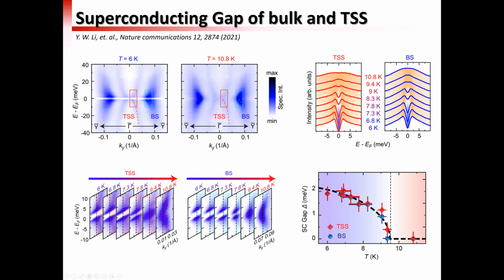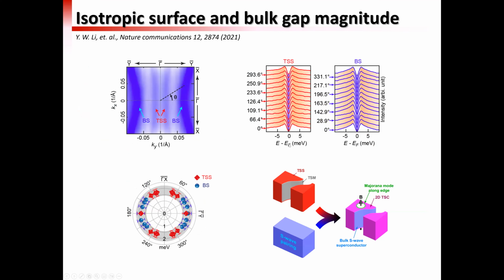And then if we just extract the data from this measurement and plot them together, you can see that starting from around 8.8 or 9 Kelvin, the gap starts opening. Interestingly, the gap magnitude of the topological surface state and the bulk state are very similar. So this leads us to think that the surface state gap comes from the proximity effect from the bulk, and I think that makes sense.